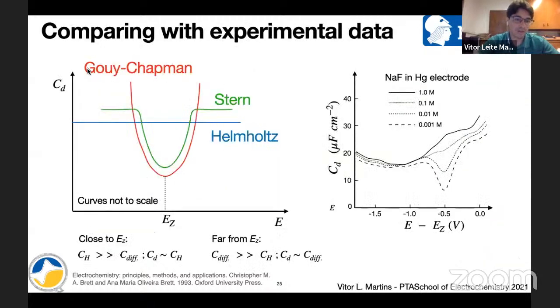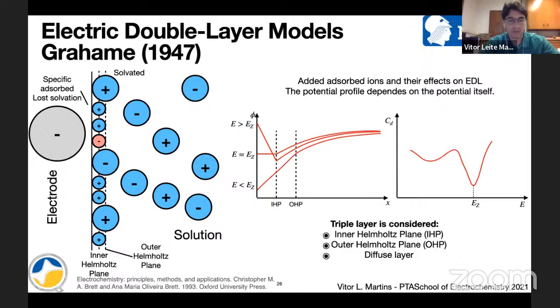So if you compare here, you have that the red one is the Gouy-Chapman, that has a nice profile for potentials near the potential of zero charge. And then we have Helmholtz that has a nice profile far from the potential of zero charge. And then we have the Stern model that combines both, and then resembles better the experimental data. Okay, so this Stern model already resembles well the experimental data, but more models were created based on that.